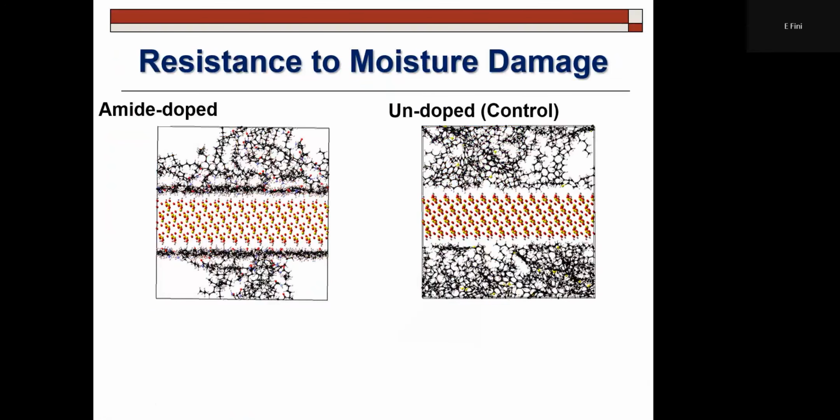In this case, you can see the molecules that we added as the reinforcement mechanism go to the interface. And in the case on the right, there is no built-in mechanism. We did not do any counteracting measure. And you can see the asphalt and the substrate are actually separating when the water comes. This was very susceptible to moisture. When I showed you this, the control sample, the TSR was pretty bad. That's the same sample. So the molecules actually go away when the water comes.